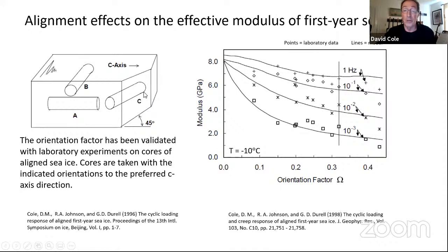We've done quite a bit of this through the years on our field cores, and this works quite nicely. You can see between the points here, which are actual experimental results, and the lines, which are the model predictions based on this orientation factor that we've calculated. You can see that there's an increasingly strong effect as the frequency decreases.